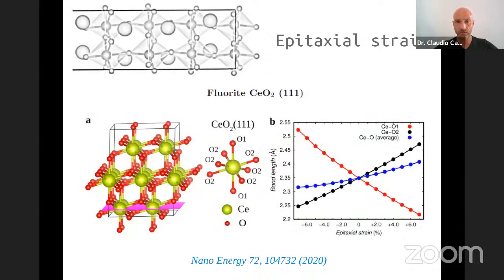Okay, so we did that. We looked into cerium dioxide, which is one of the best known catalyst materials, or most extensively studied, right? And what we did was to look into how the structural and electronic properties of this material changed under these epitaxial strain conditions, right? So we explored both tensile, represented by positive epitaxial strain in percentage, as well as compressive when these numbers are negative, right?